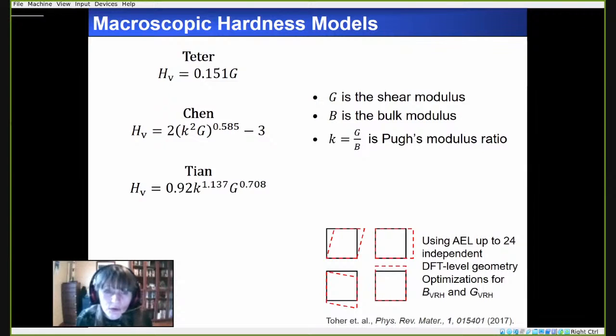The other reason is if you look at the dimension of the Teter model, it's going to have the dimension of GPa, whereas here you have strange dimensions coming out of it. And also this coefficient in the Teter model was actually developed theoretically based upon the shape of the Vickers indenter, whereas the Chen and the Tian models, these numbers here, were developed by fitting to experiment. So those are the three reasons why we chose it, the first one being the most important. However, I have not explored regions where the Chen and Tian model might be more appropriate for predicting the hardness of known materials.